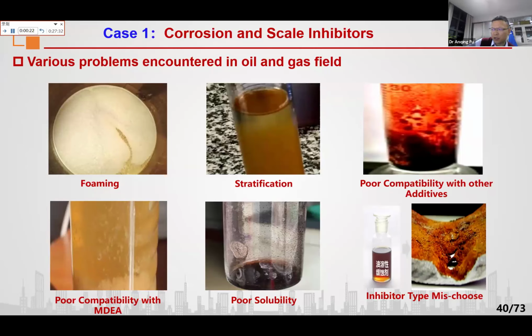Unlike the theoretical research in our lab, the physical properties are as important as the inhibition efficiency and the inhibition mechanism. Here, I give some typical examples of the inhibitor physical properties problems encountered in the oil field. We can see the foaming, stratification, and poor compatibility with other additives, the poor compatibility with the MDEA, which was used for the oil and gas treatment solution, and another one is the poor solubility in the water or in oil phase. The last one is the inhibitor type mix-ups.